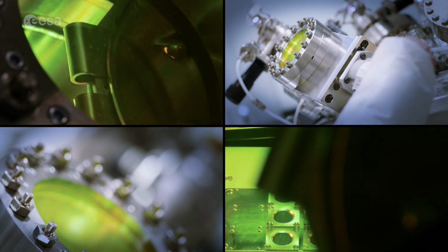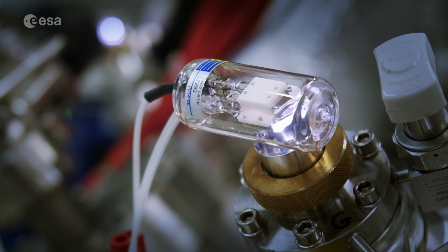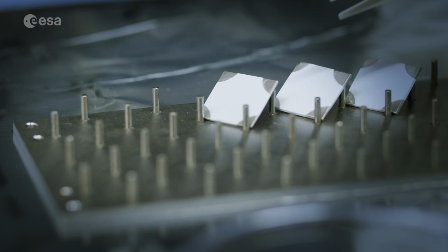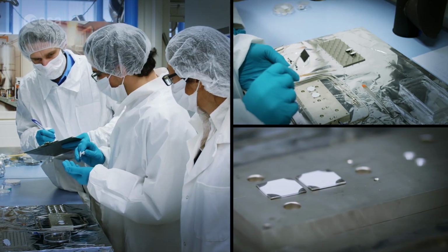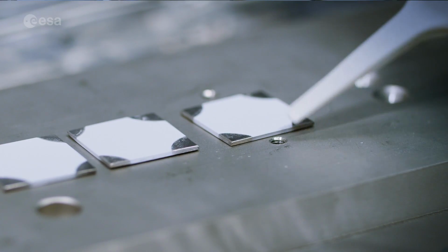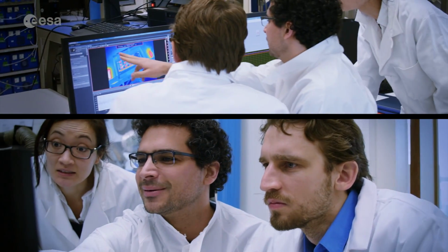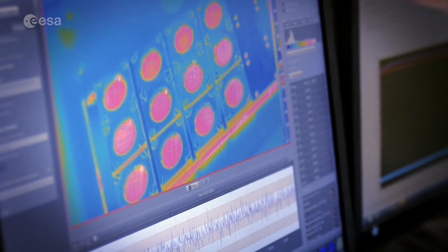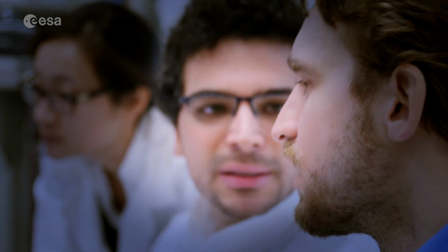The ESTEC STAR2 facility is a facility where we can expose samples simultaneously to UV intensity and radiation particles, simulating the harmful part of the sun and measuring at the same time the performance of the material as if we were in space. For the antenna, it was important for us to test its ability to reflect the incoming radiation and emit the heat. These two properties, referred to as low solar absorptance and high thermal emittance, help us to regulate the temperature of the antenna, which we aim to keep below 450 degrees Celsius.